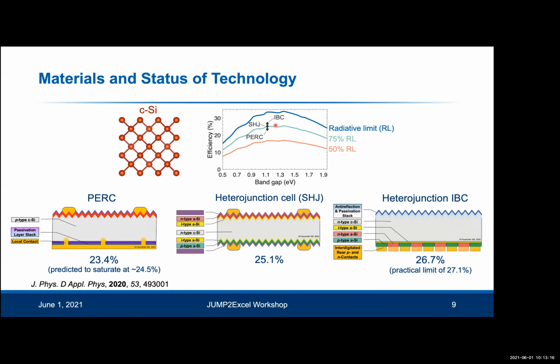And over here, I have a comparison of the efficiencies of these different technologies compared to the theoretical radiative limit for different band gaps. You can see that these best efficiencies are scattered about the 75% of the radiative limit line. I should mention that even though for a material with a band gap of 1.12 eV, which is silicon, the theoretical limit is above 30%, in reality, the maximum efficiency that you can achieve with this material is lower than that and is limited by Auger recombination. So actually the highest efficiency you can get is about 29%. You can see that after 6 decades of development, silicon technology has now approached its efficiency limit.